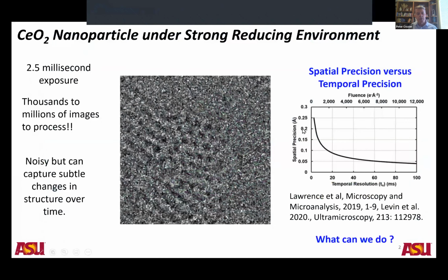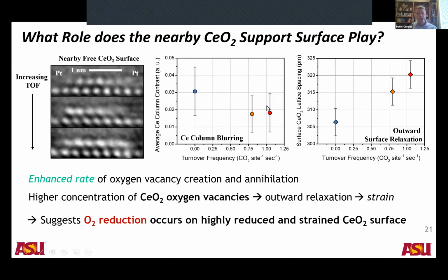Let's just go back here. What we're finding is that the fluxionality that we're observing in this case, associated with reconfiguration of the platinum nanoparticle and the distortions that are taking place on this area, are all correlated with the catalytic activity. And in fact, it's the creation and annihilation of those oxygen vacancies. What that's doing is it's debonding the platinum nanoparticle from the surface of the ceria, which is leading to this rapid reconfiguration of the platinum nanoparticle.